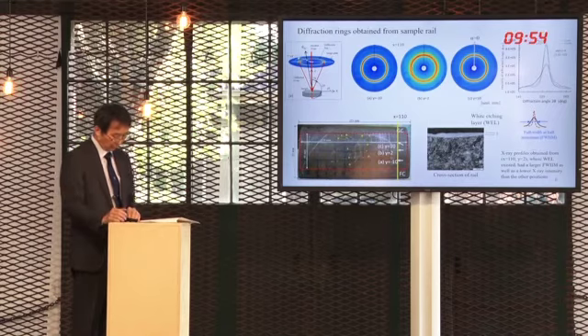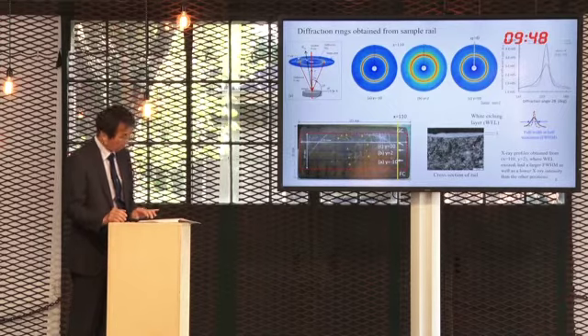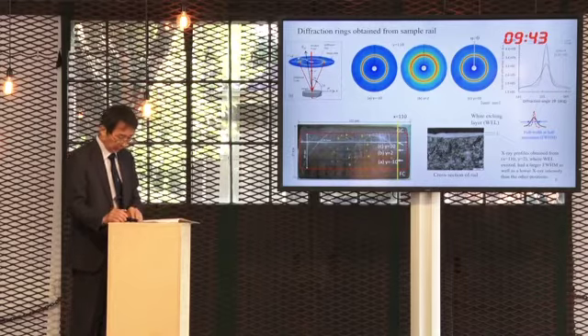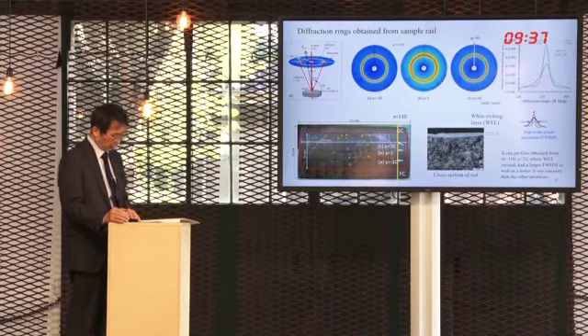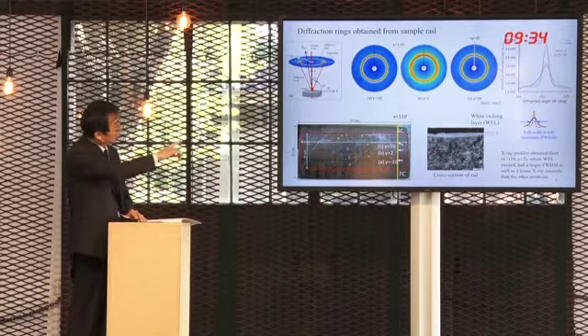This slide shows 3 examples of the diffraction rings obtained from the layer. These were measured from the positions shown by the white arrows in the picture at the bottom. We can see the width of the second diffraction ring is thicker than those of the others. The right top figure shows the profiles of the intensity of the diffracted X-rays in the radius direction from the center of the diffraction ring.